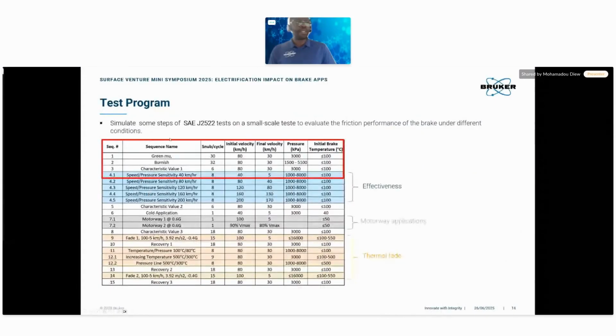If you use this tribometer, taking only a few step sequences from the AK Master, for example the SAE J2522, we can run these 4 steps, and we limit ourselves to these 4 steps because we are using a 3-pin and a 1-pin configuration. Due to the torque limitation of the system, we limit ourselves to the first steps and compare different solutions. Sometimes it's enough, depending on your applications, to get the comparison of different solutions. Because at the end, as already said, and as we already claimed, the tribometer is not here to replace the dyno. It's only here to help do a screening of materials and go further if you want with a dyno.